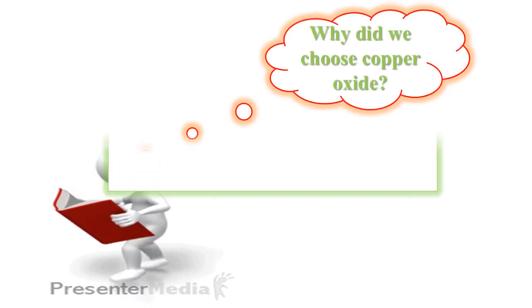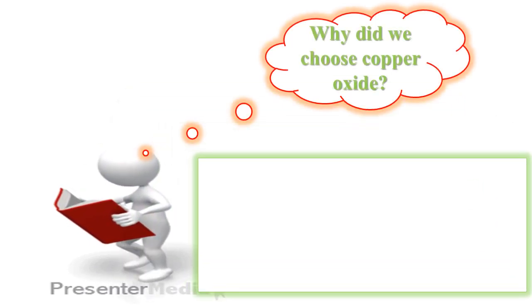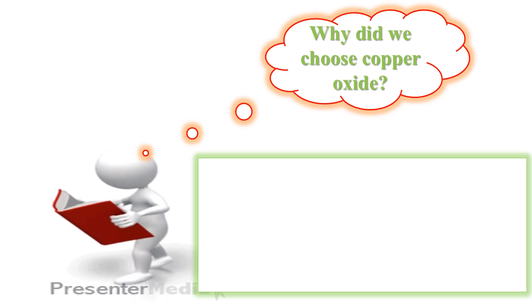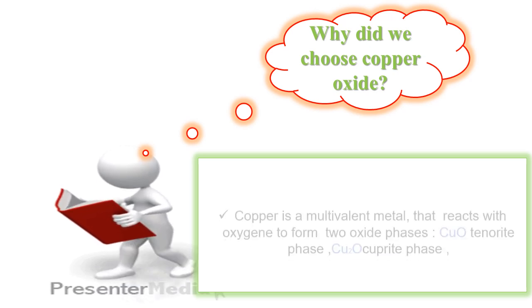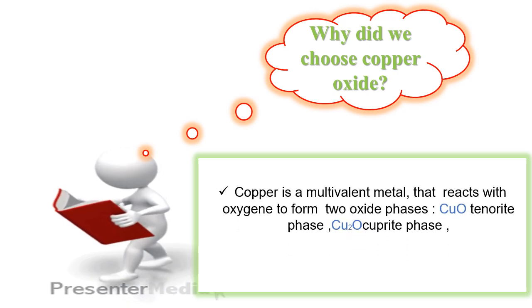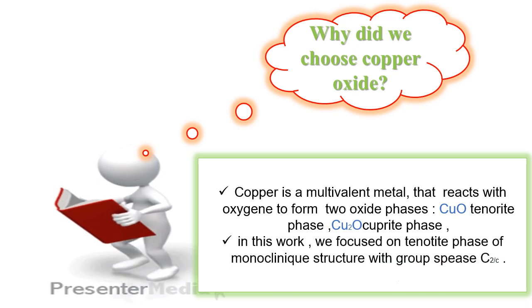Reason for choosing copper oxide. Copper is a multivalent metal that reacts with oxygen to form two oxide phases, the tenorite phase and the cuprite phase. In this work, we focused on the tenorite phase, of monoclinic structure with space group C2/c.